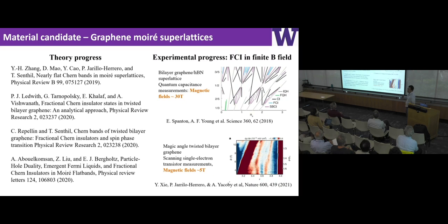Indeed, there has been quite a lot of exciting progress showing fractional Chern insulators, but in the presence of a magnetic field. The first work is from Andrea Young's group. They studied the moiré superlattice formed by bilayer graphene and hBN, and found fractional Chern insulator states in the presence of above 30 Tesla of magnetic field. Then a collaboration between Pablo and Amir showed that in magic-angle twisted bilayer graphene, these FCI states can exist at low magnetic field, showing up starting at roughly 5 Tesla. Both experiments establish thermodynamic evidence of FCI states, but in the presence of a magnetic field.